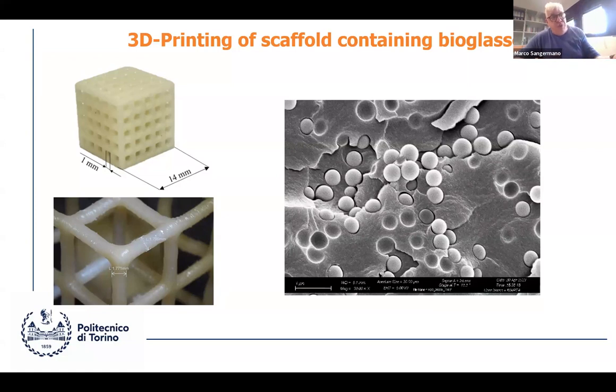The precursor was bio-based, soybean oil, so extracting oil from soya, functionalized, dispersed bioglasses, 3D printed, getting these complex 3D structures, and getting a scaffold to allow cells to grow. So those scaffolds have mechanical properties comparable to the properties of bones, and so they can replace bones and allow the cells to grow on it.